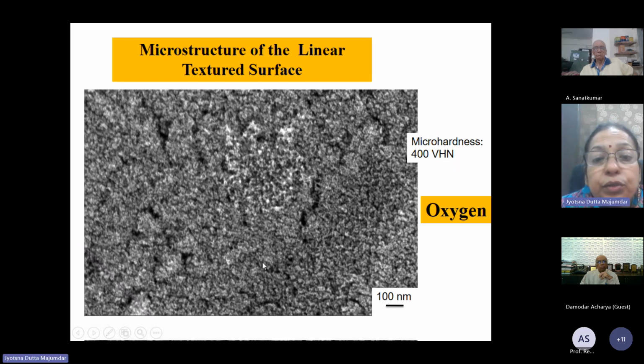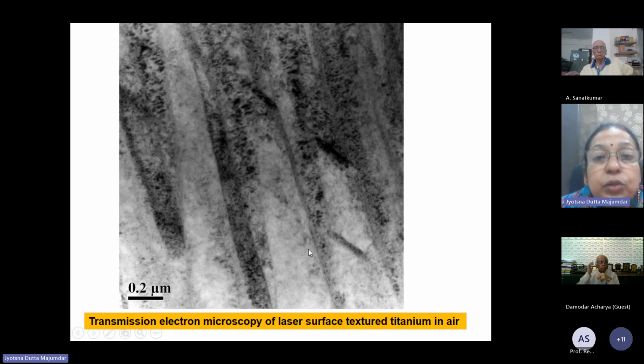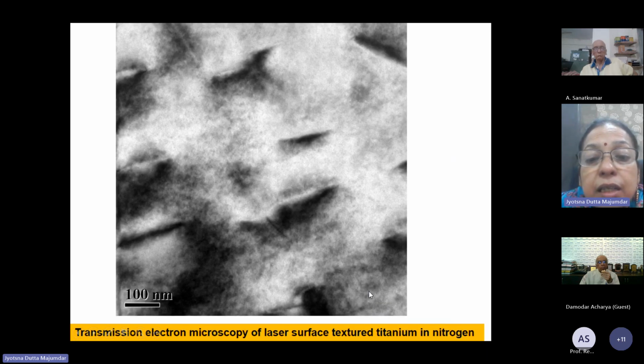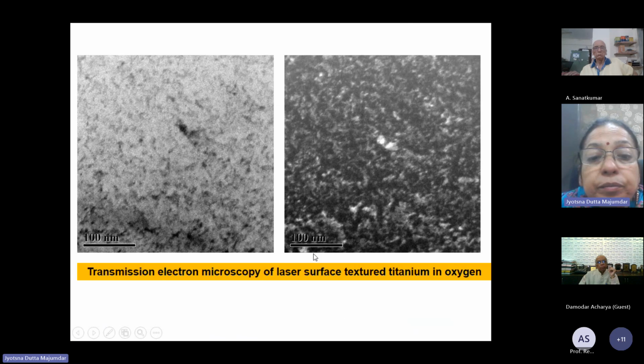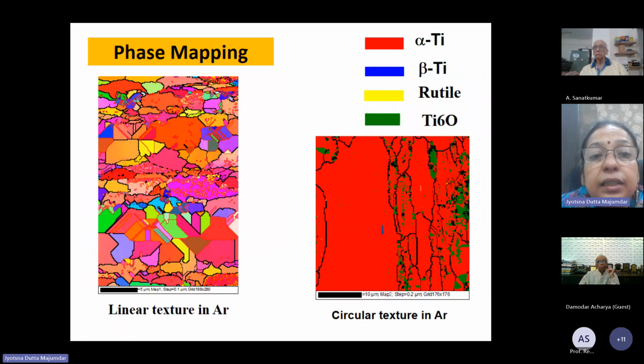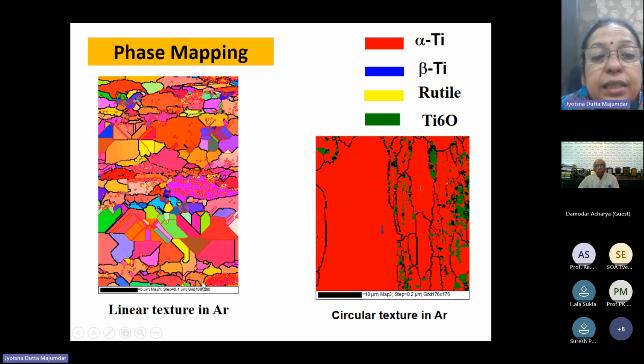In the linear textured surface we found, as I said, that in the oxygen environment a very thin oxide film was there on the surface. We did this in three different environments: air, oxygen and nitrogen. Here we find patches of oxides present, and oxides in the form of very fine dots and precipitates, and in the nitrogen environment nitrides are also present all throughout the surface. In the oxygen environment we find a lot of oxides on the surface. These were actually confirmed by TEM analysis.